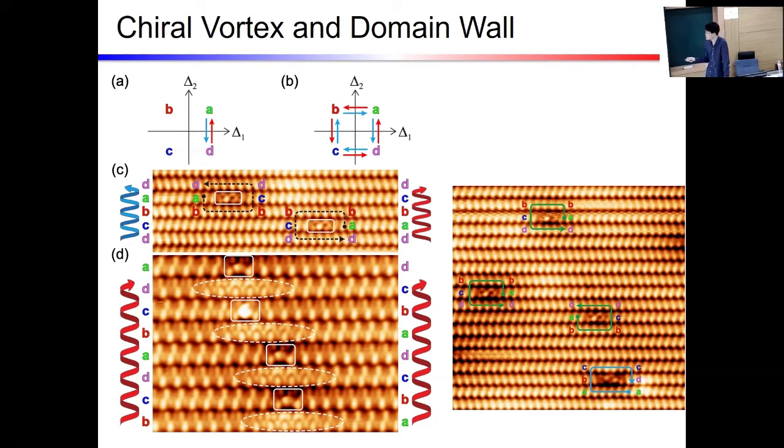But for the other defect, this single defect, this is a double defect, coming together, then B translates to D, right? Starting from A, B, C, D in this direction, the winding now becomes clockwise. So the defect also gives some chirality. This kind of structure people call a chiral vortex.